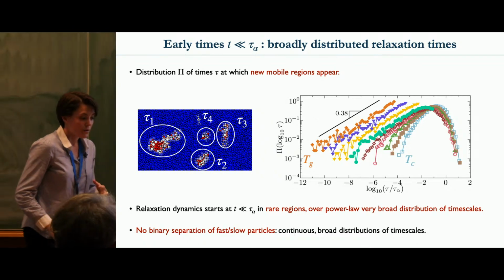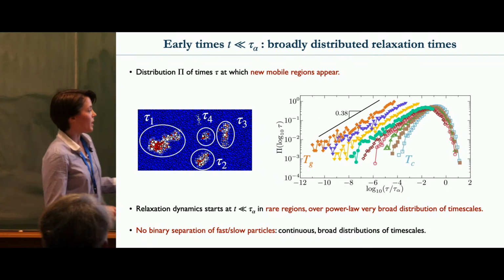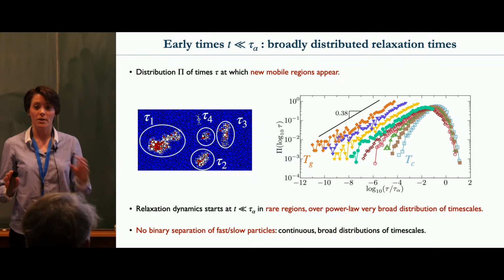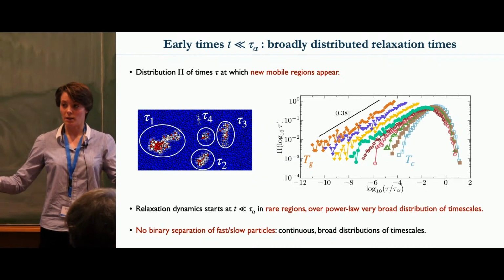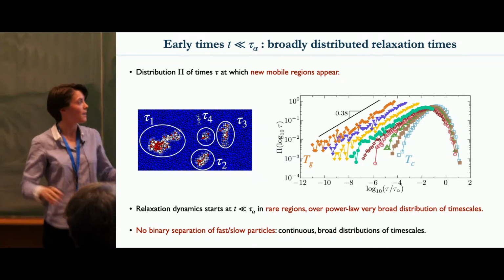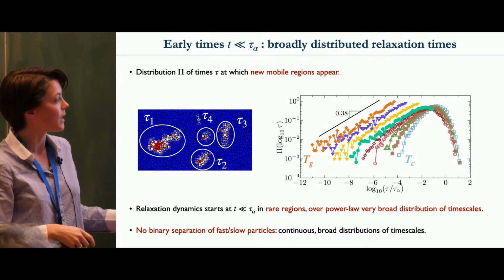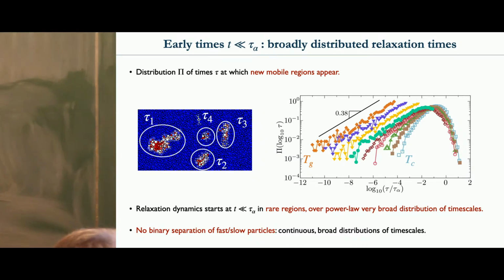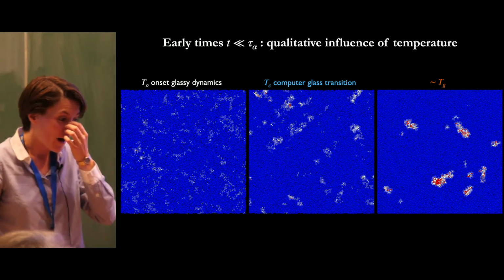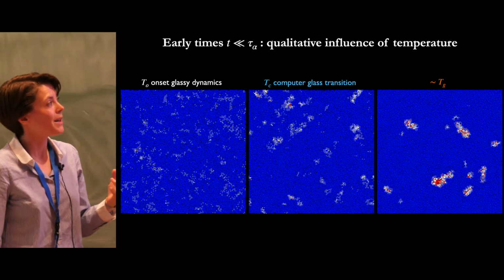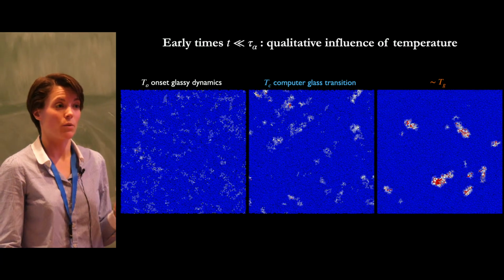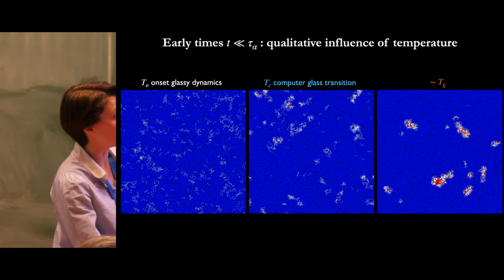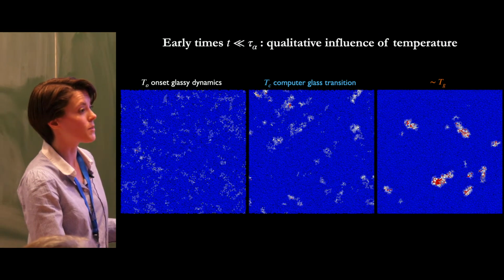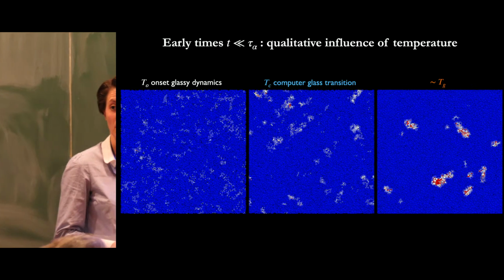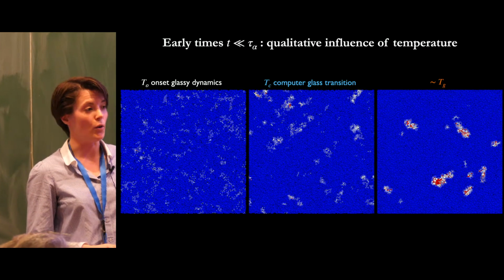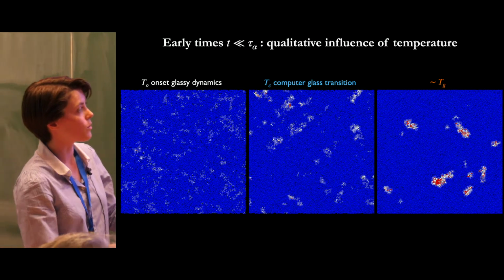So maybe an important point that I want to make here is that there is no binary distinction between fast and slow particles. There's a continuous and extremely broad distribution of timescales, over several decades. Now, I want to show you what's happening at higher temperature, which is what people are more used to. Here I discussed the very low temperatures that correspond to temperatures close to the experimental glass transition, so really completely new physics that we're observing.